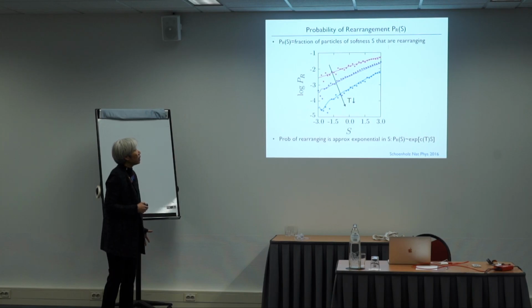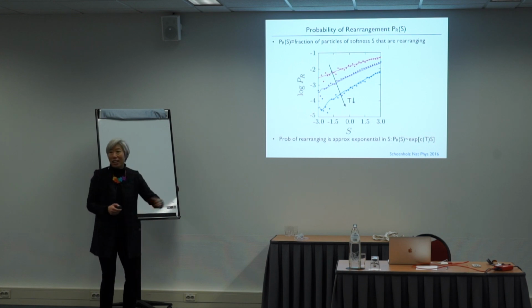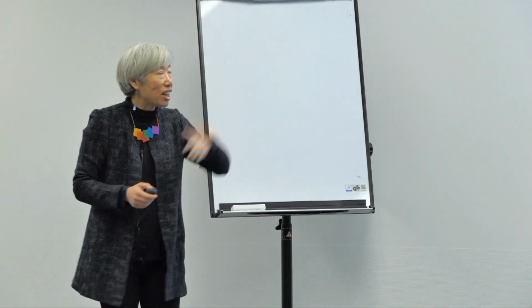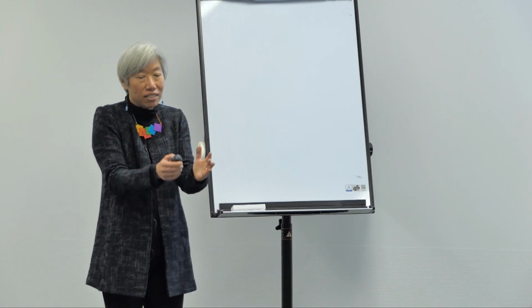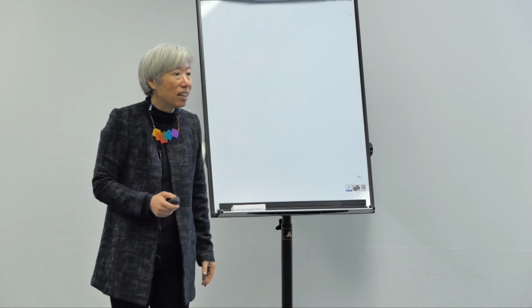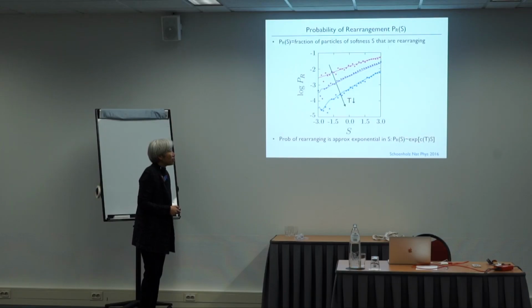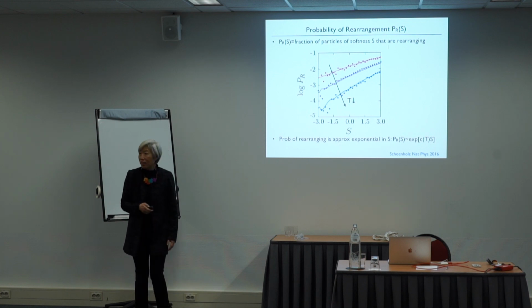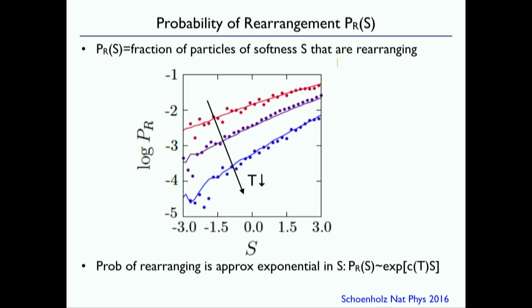So now it's quite interesting if I look at the probability that a particle that has a given softness will rearrange. So I just count what fraction of the particles at softness S are rearranging in any given time step. So it's the probability per unit time. That probability of rearranging at a given softness turns out to be roughly exponential in softness. So this is the log of that versus softness. It's roughly exponential in softness.